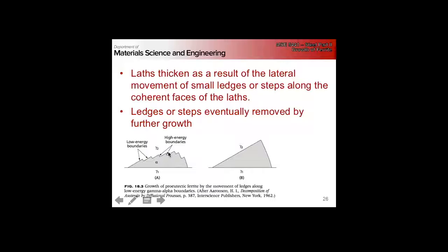So we can actually have thickening of the laths without breaking that coherency, without destroying the coherency of the interface. We're not forcing that coherent interface to move.